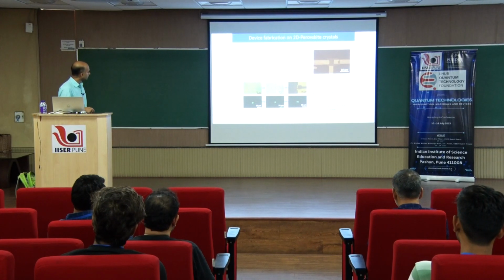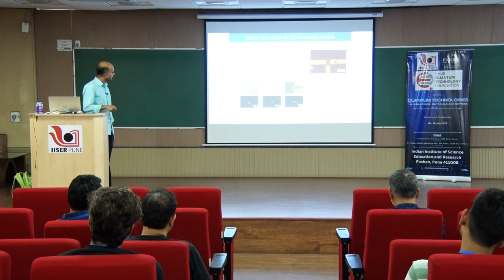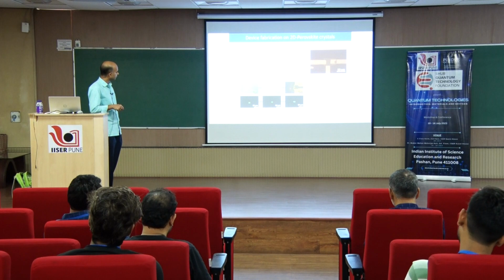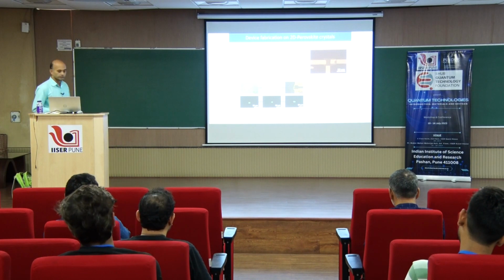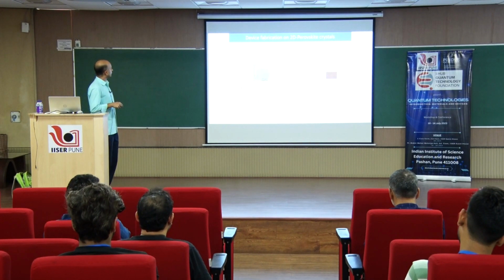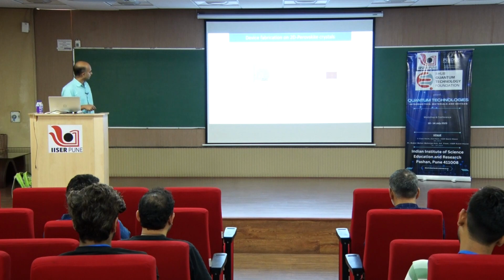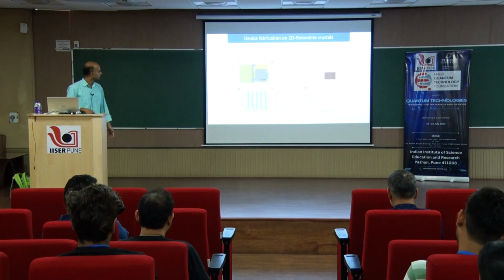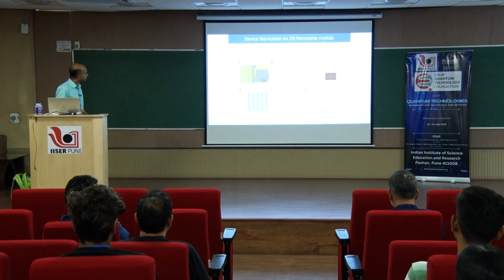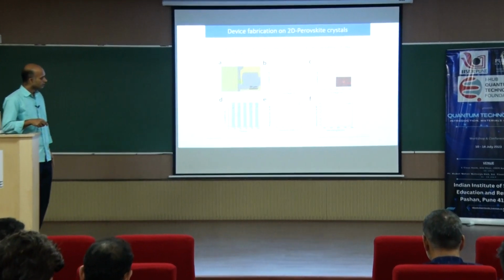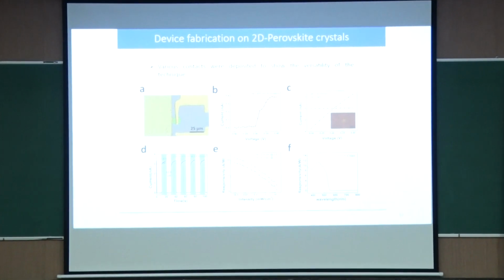At each and every step, you can see the PL remains intact. Here we deposited the gold pads, so the PL is not there. You can see that they are showing decent electrical properties. We even checked with various other materials, like in this case, we have tested with gold and aluminum, so it shows a diodic behavior. Here I think this is with indium tin oxide, transparent conductor. We made the connection using that.